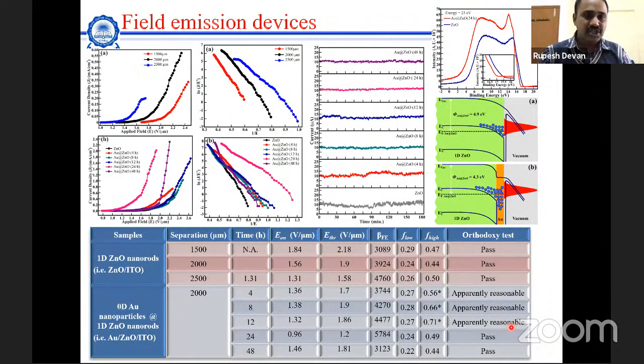So when we check the field emission for this zinc oxide, the lowest turn-on field was 1.31. But as soon as you go on increasing the gold concentration, you can change the turn-on field from 1.31 to 0.96, which is really less. What happens over here? You can see the stability remains almost constant, and compared to earlier reports it is far better. What happened after coating the gold?